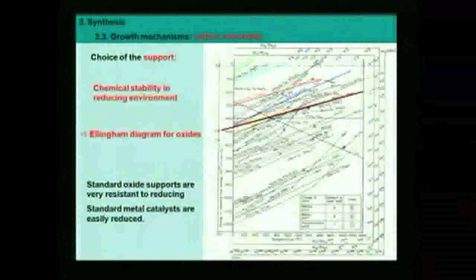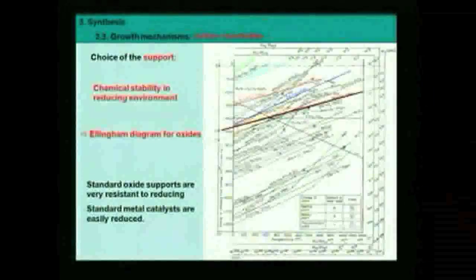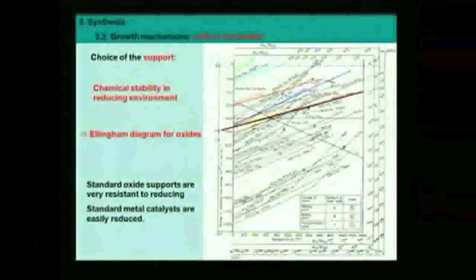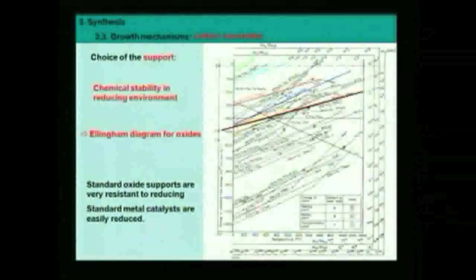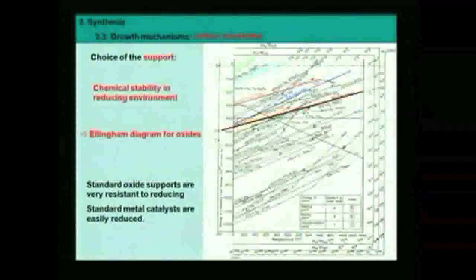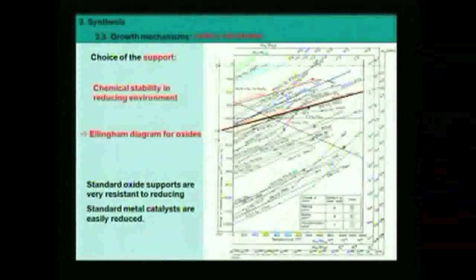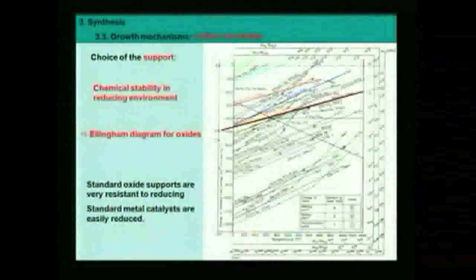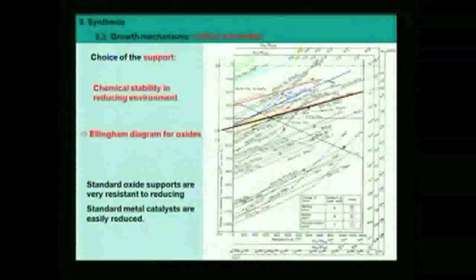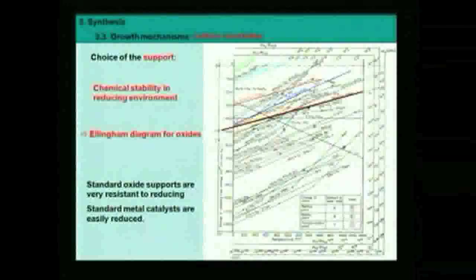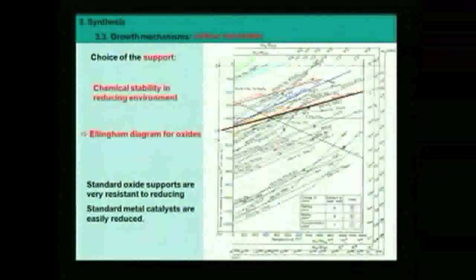Now we are going to use catalysts like iron, nickel and cobalt. We don't want them to be oxidized because as oxides there will be less active catalyst. So we want them to be reduced during the synthesis. So, is it possible? Iron is here. We have nickel here in blue. We have cobalt. Where is cobalt? Cobalt is here. Okay, so all of them are here. And you observe that they are quite stable oxides. They are not metastable. They have a negative free energy of formation. So they are stable oxides, but they are less stable than the oxides used as support.